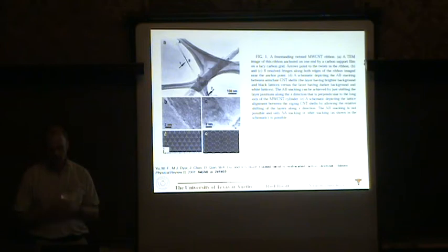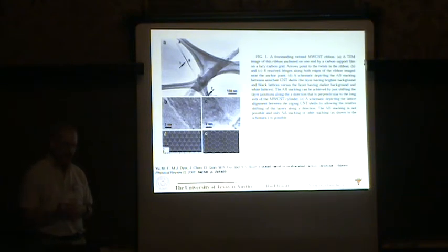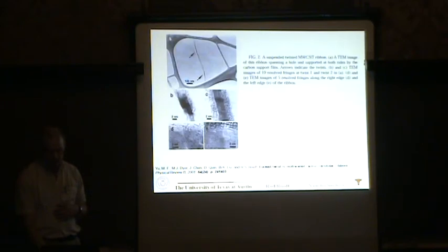And so there was already a ready-made model in terms of the energetics for us to consider. So the hypothesis was that this is one of those sorts of tubes that, by twisting, can achieve a better interlayer registry in the collapsed inner shell than if it were not twisted. And that's pretty much where we stopped. I mean, we mapped out the number of layers and so on, but we couldn't really prove that hypothesis. It just seemed to be sensible.